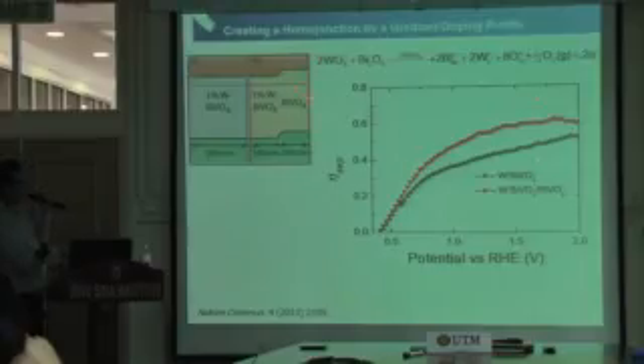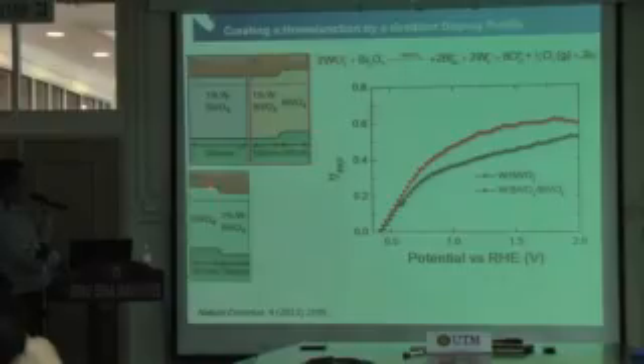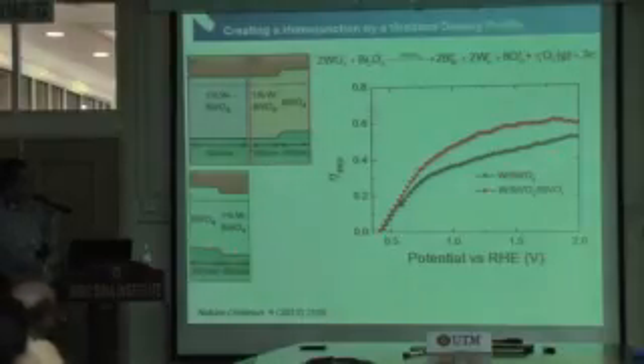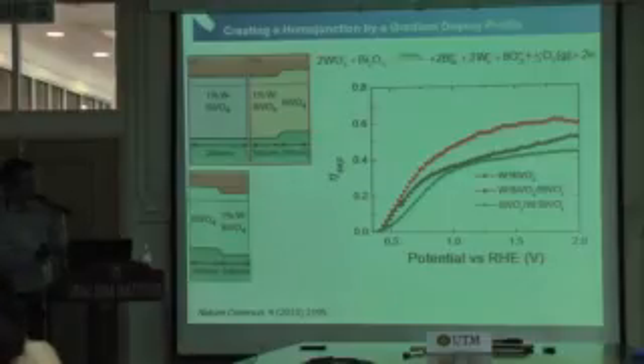To check this, we then reverse the junction. We make it the other way around. Now, this is then a barrier, so electrons will see it as a barrier. Holes will also see it as a barrier. And you would expect it to be lower, and indeed that is actually what we measured.